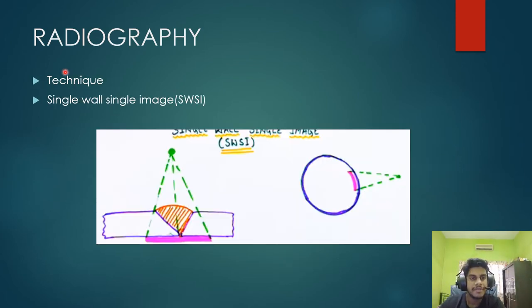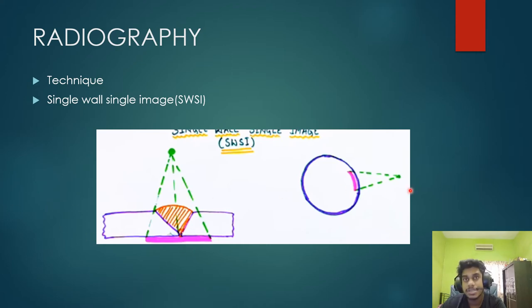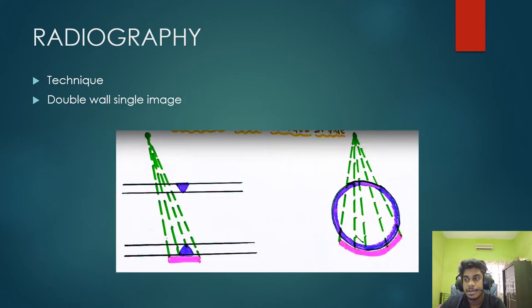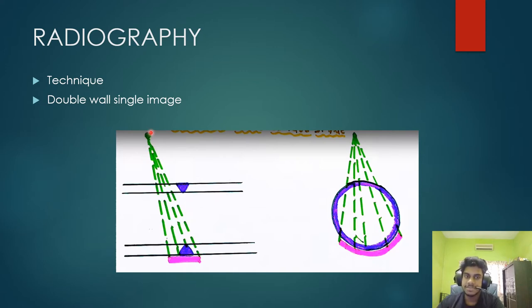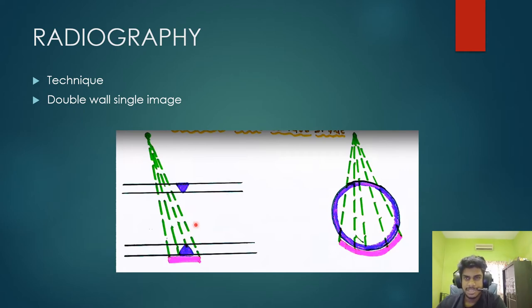This is radiography single wall, single image. The radiation source is on the outside and the film is underneath — it is the simplest form. This technique is called double wall single image. Through a double wall, there is an offset angle which ensures they capture the welding spot underneath the weld. This is very useful especially in tubes where you want to image the underside and not the top side, and where there is restriction of angles.